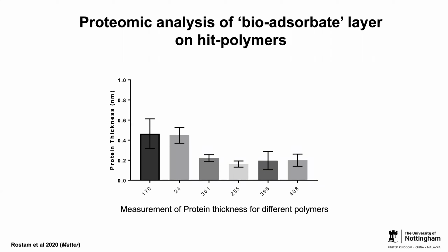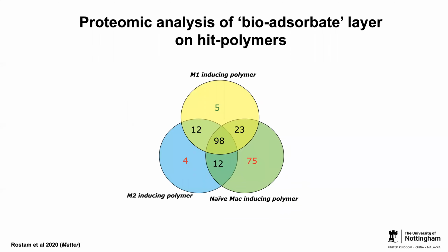And here it just shows you the XPS analysis of 6 of these polymers. The first 2 are 2 of our pro-inflammatory polymers. And you can see that the thickness of the protein layer seems to be consistently higher than everything else. But if you look at using proteomics on the actual nature of these proteins, you can see that although there are some common proteins present on both M1, M2, and naive macrophage inducing polymers, we have also identified a number of unique proteins that are present on these different groups of polymers. And that goes some way to explain probably why they have the ability of differentially promoting polarization of these cells.